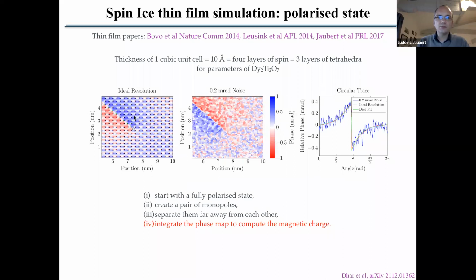And you can see that if you simulate the electron microscopy measurements, you can measure the phase map. And this phase map is very similar to what we had before, with a discontinuity of the phase map at the level of the Dirac string, but it starts negative, then goes up, goes up, goes up until it becomes positive there. And so that's what you can see here. And even if you add numerical noise to simulate the noise of experiments, you can recover the value of the magnetic charge with this jump here, which corresponds to the value that you can expect theoretically. So this is a simulated proof of concept that the same experiment can be done on a thin film of spin ice.